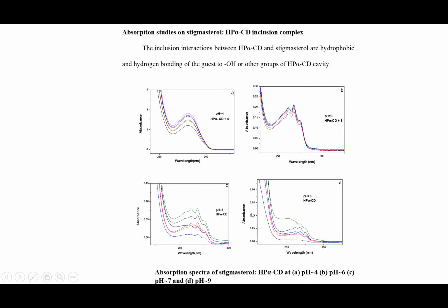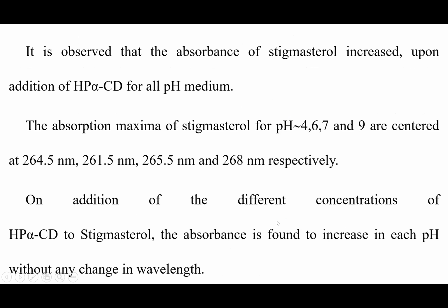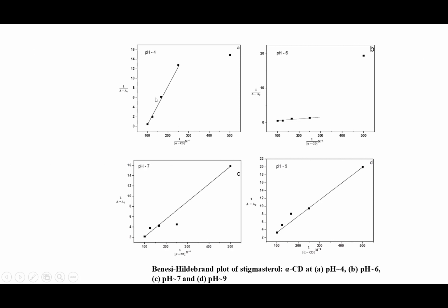Similar results are obtained in these both complexes also. So here, on addition of HP alpha CD at different pH, the wavelength remains the same. In some cases, it varies with a different peak. So this is the graph plotted between 1 by concentration of alpha CD as well as 1 by A minus A naught. We get a straight line. From the straight line, we calculate the slope, and from the calculated slope value, we calculate the binding constant using the Benesi-Hildebrand equation.